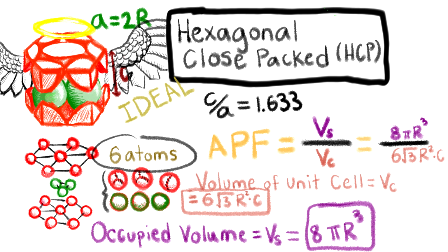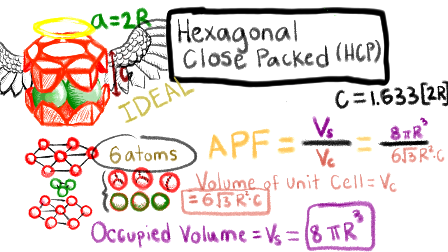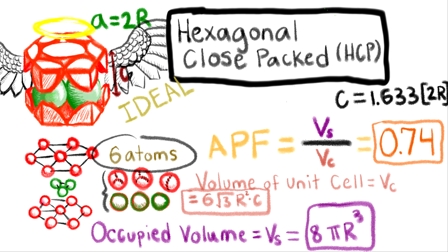It also turns out that the vast majority of HCP structures are ideal, so unless you're working with one of the exceptions, you're free to use this relation. Rearrange C to isolate it and plug in the value of A. Drop the value for C into the equation for the unit cell volume. Sure enough, it comes out to be identical in packing to the face-centered cubic.